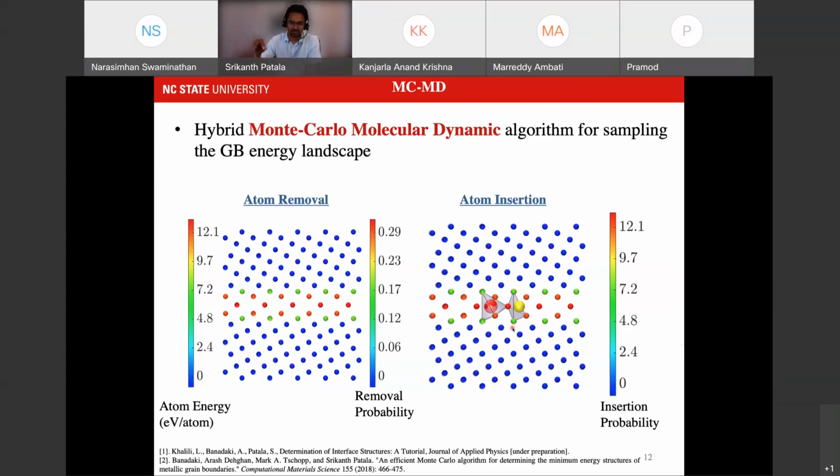But one of the reasons I wanted to go with Monte Carlo is there are extensions of Monte Carlo that can help you, for example, do ensemble specific simulations. For example, if I'm interested in a grand canonical ensemble, and I want to know what the free energy of the interface is, it's more obvious how to do it in Monte Carlo. You can do it in genetic algorithms too, but it's much more complex how to set that up. Given its historical context, the technique is much more well developed for generating ensemble specific distributions. And that's the main reason why we went with this.